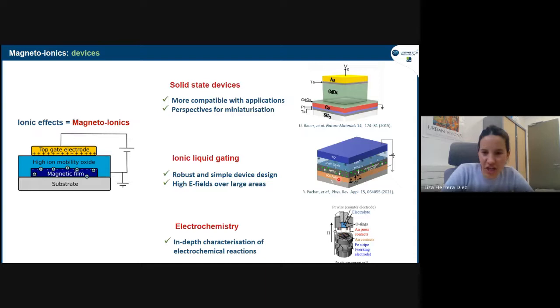And it can be done over large areas, which allows you to measure, for example, XPS or XAS techniques, where you would like to have a relatively large area that you can measure. So it's very useful to understand the mechanisms. And then I will show you some of our work done with ionic liquid gating. And as I said earlier, most of the things happening here are related to electrochemical reactions. So the metal turning into an oxide and back and forth through the action of a gate voltage.